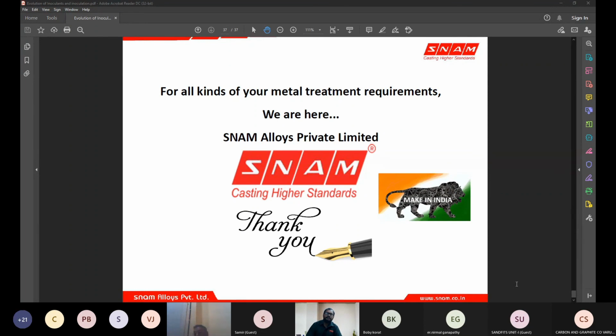But the problem is, in your furnace, your temperatures are high and your volume of metal is high. So instead of going for inoculant, there are special materials which perform with a greater potency than inoculant. A preconditioner is like a super inoculant. That can be added at the same addition rate, say 0.1%, which will give you a better effect than what you're doing right now.